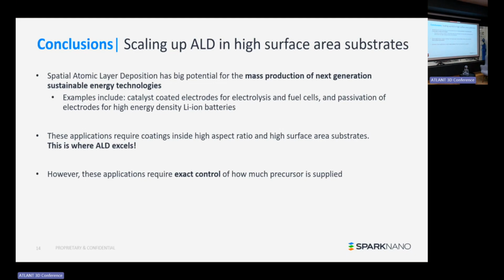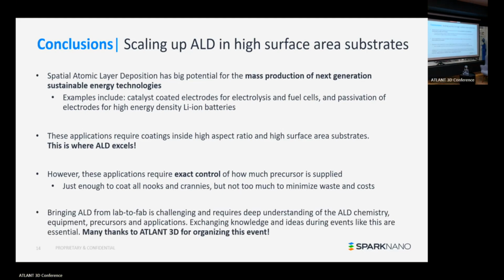However, it does require exact control of how much precursor we deposit, either because we have to supply massive amounts and you need to be able to handle that, or we work with precursors which are very expensive and use scarce elements. So we need to supply just enough to coat all the nooks and crannies of your substrate, but not too much, to minimize waste and costs. So bringing ALD from lab to fab is challenging on many levels. I'll just give you one example in the case of the precursor supply. And doing this requires a deep understanding of the ALD chemistry, equipment, precursors, and application. And of course, exchanging knowledge and ideas during events like this is very important to do that.